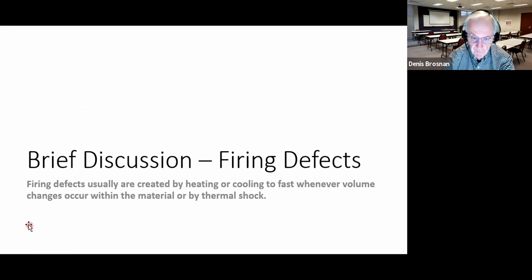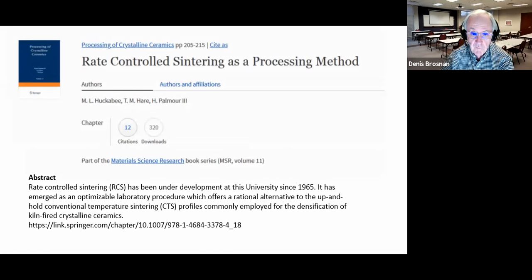Okay, now let's talk about firing defects. They're usually created by heating or cooling too fast in the kiln schedule. Okay, so I did a little bit of quick internet research and found this reference about controlled rate sintering, or rate controlled sintering. One of these gentlemen was a professor, Hayne Palmour, and you can see the abstract there. I found it on the internet, rate control sintering, and he proposed rate control sintering as a means of designing a firing schedule. And it is, in fact, the way that a lot of people designed firing schedules in the past. So whenever there's a change in dimension that is fairly rapid, people will slow down. And that certainly is true, especially with cooling in ceramics that contain quartz or cristobalite. So I wanted to point that out to you.